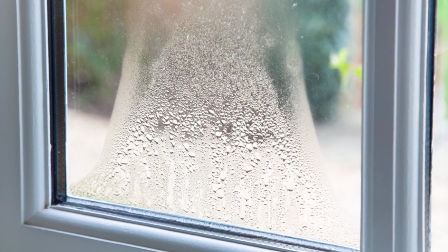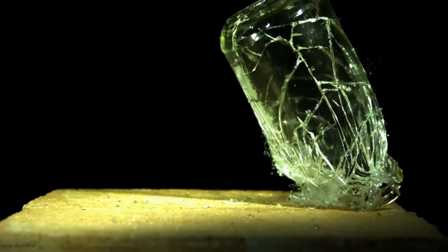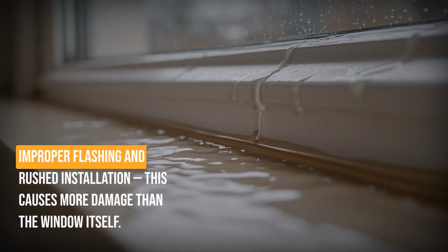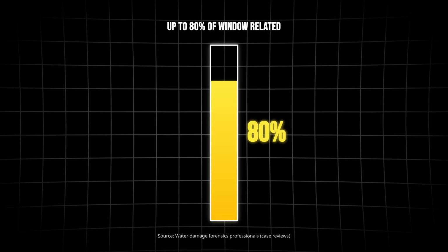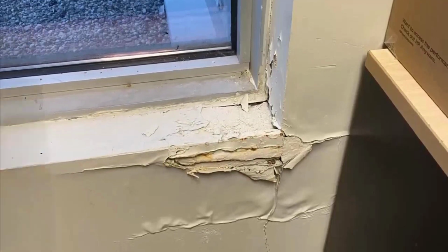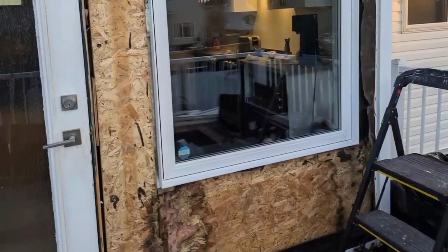The data on when these actually start failing is worse than most people expect. This one causes more damage than the window itself. According to water damage forensics professionals, up to 80% of window-related water intrusion traces back to improper flashing or installation, not a defective window unit.